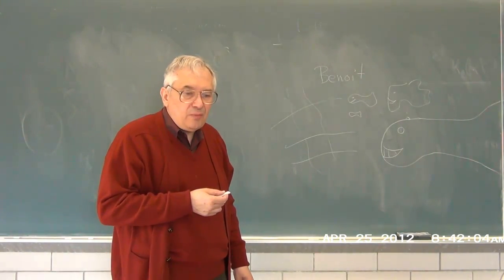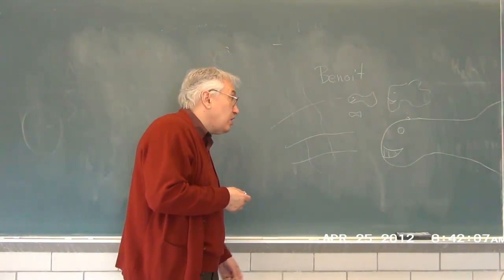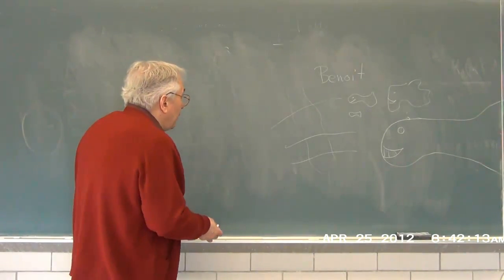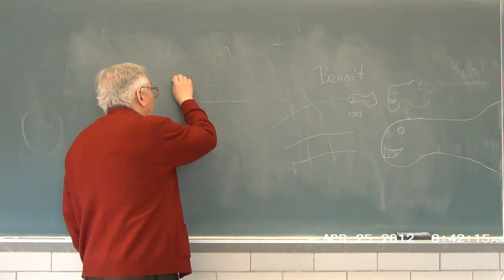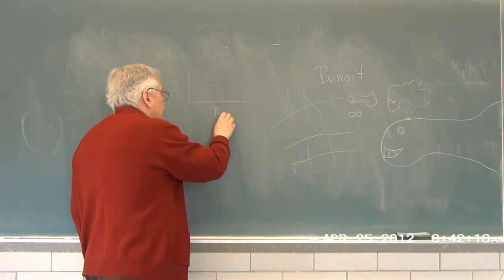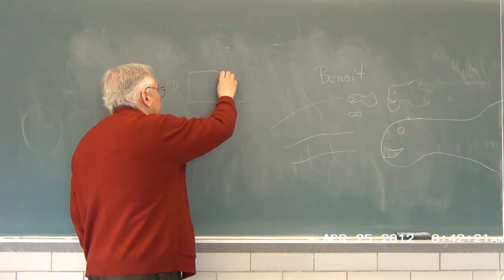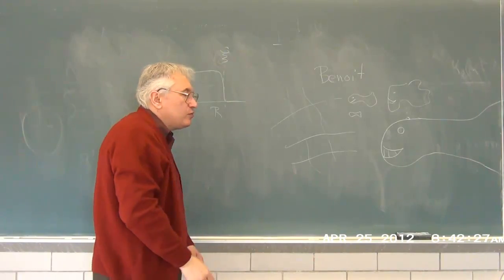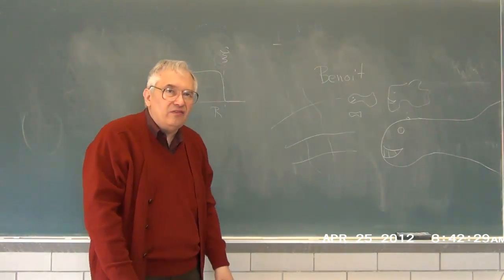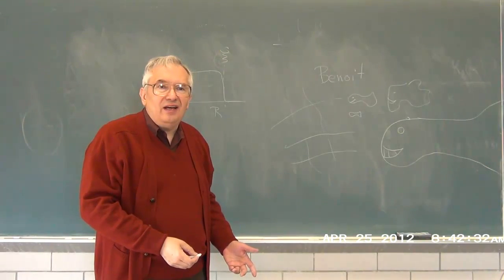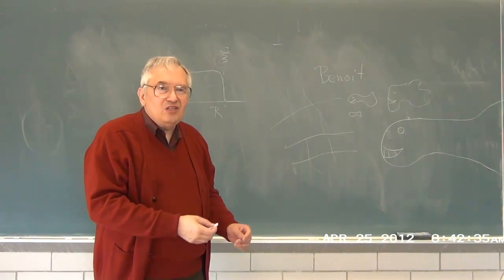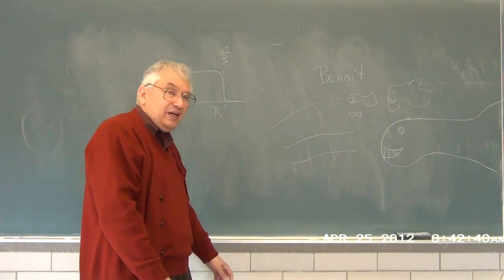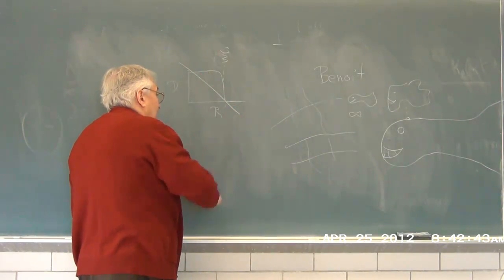You can do the experiment with optical probes and light scattering. And the impression you would get from this picture is that if I plot diffusion coefficient versus R, there is some size and over some range. After all, this is a random lattice. The large particles are blocked and cannot advance other than very slowly, and the small ones can swim right through. Well, that is what this model predicts, and it's really not true.